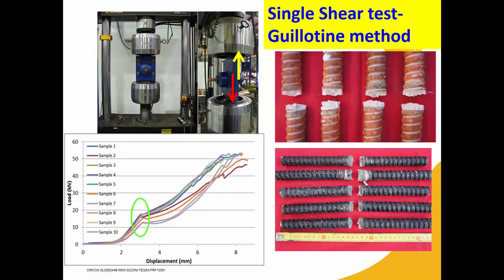Single shear test, or guillotine shear testing, was carried out to determine the pure shear strength of the sample. The samples were cut into small pieces and positioned inside this guillotine box, and the whole assembly was positioned inside the tensile testing machine. You can see here that by having extension, the sample is subjected to shear loading.